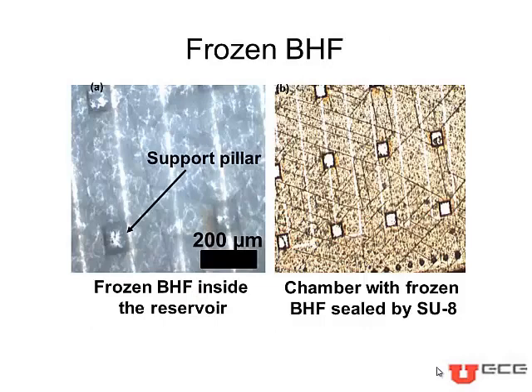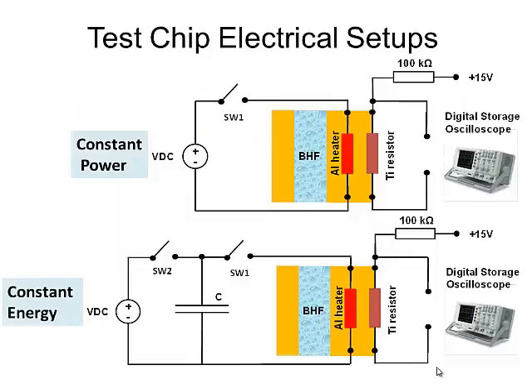These pictures show 2 important stages during the freezing process of the sample. The picture on the left shows frozen BHF after flash freezing and air drying, while on the right we see frozen BHF after spinning and exposing of SU8. Our test device was subjected to 2 types of electrical tests with the setups shown below.